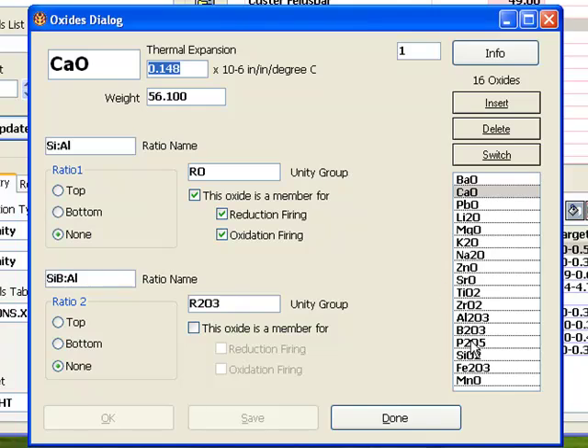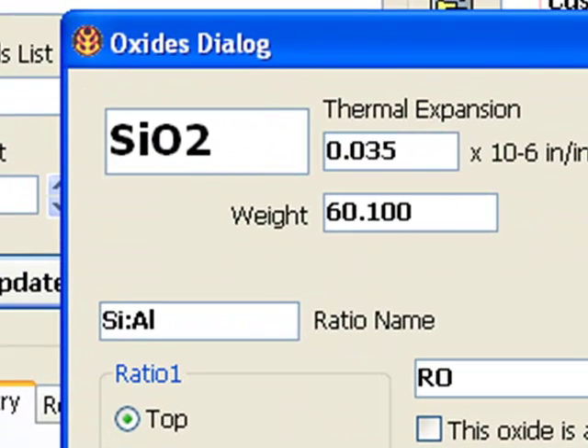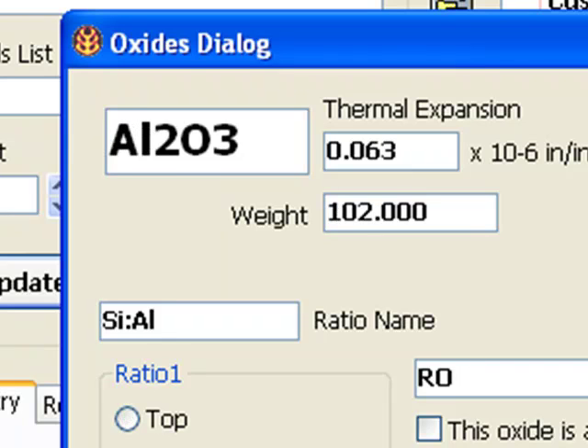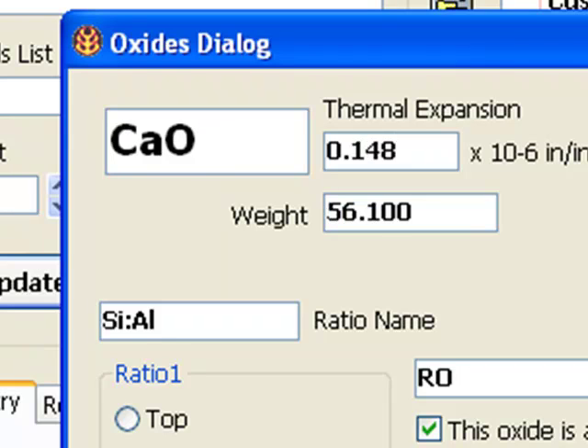Now I'll click on the SiO2. This is more than four times lower. And alumina? It is more than twice as low as CaO. But now look at Na2O. It's more than twice as much as CaO, the highest of any oxide. So in a relative sense, CaO is a low expansion flux compared to sodium. Potassium is also really high. That is why high feldspar glazes often craze. They contain a lot of sodium and potassium.